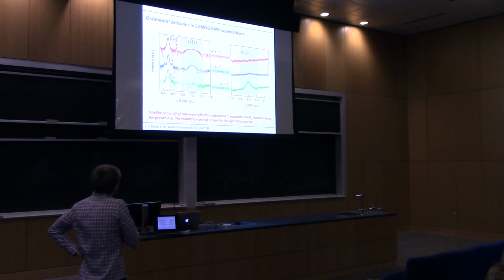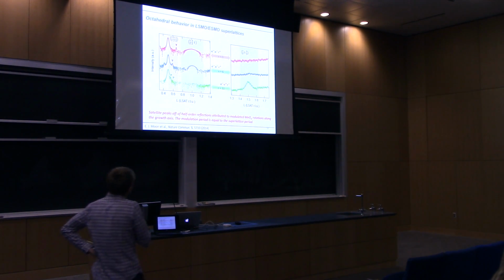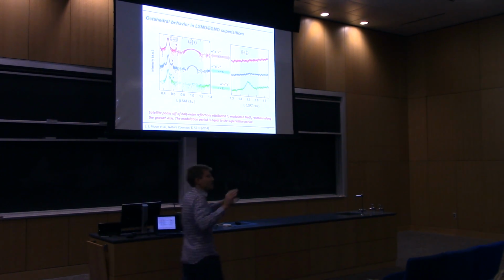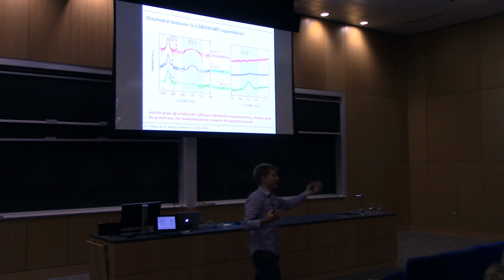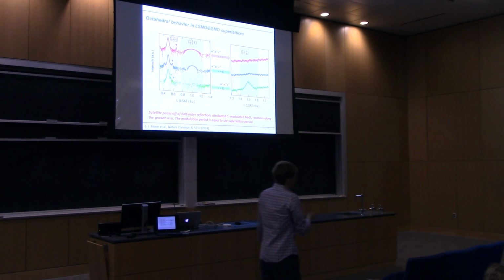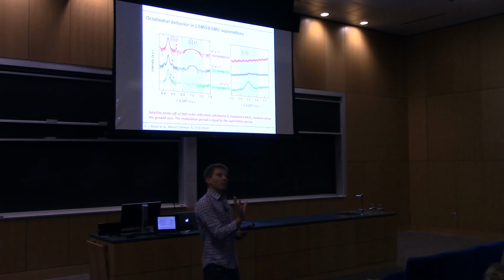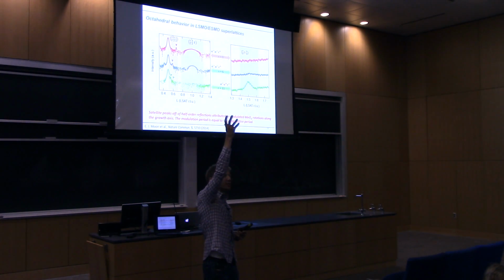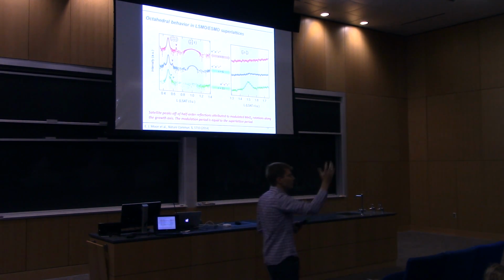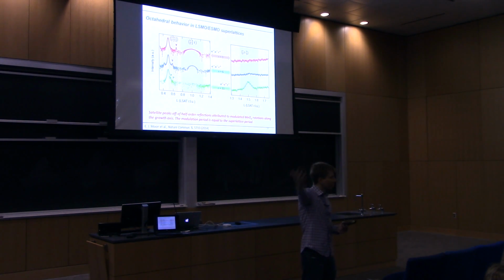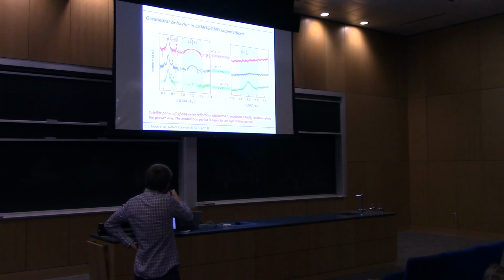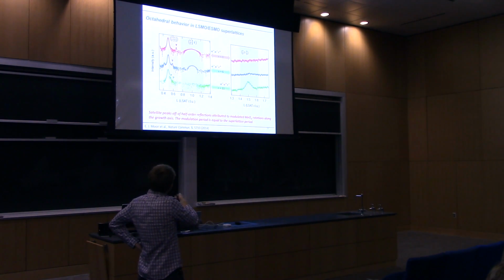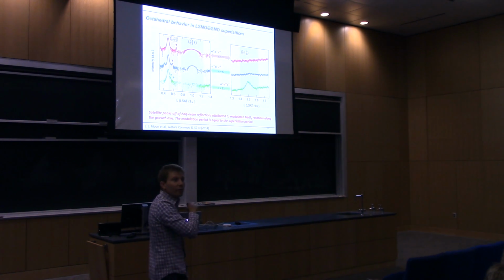I mentioned those half-order diffraction peaks. Okay, so again, these are half-order diffraction peaks that arise from the unit cell doubling of these octahedral rotations. So they're sort of like satellite peaks in some sense. And this idea that we have these modulations of the octahedral rotations. So anytime you have a periodic modulation in a crystal structure, that will also give rise to a diffraction peak, right? And so we in fact see that, and these are the 3 different superlattices again, we see a satellite peak off of the half-order diffraction peak, right?